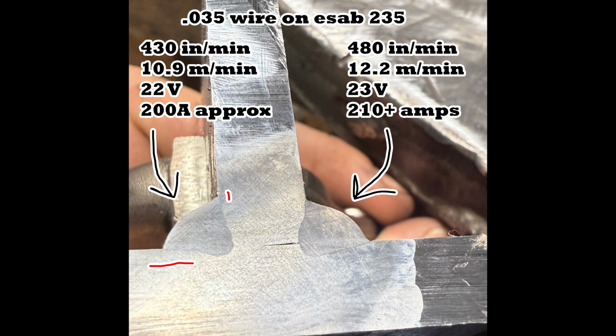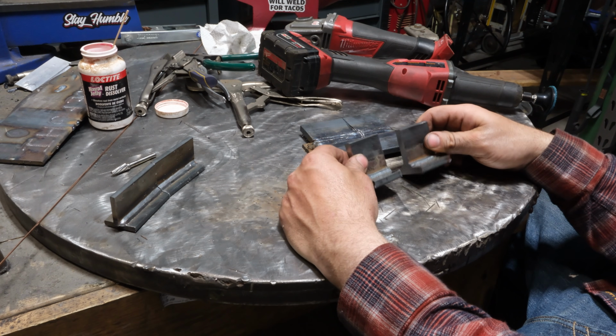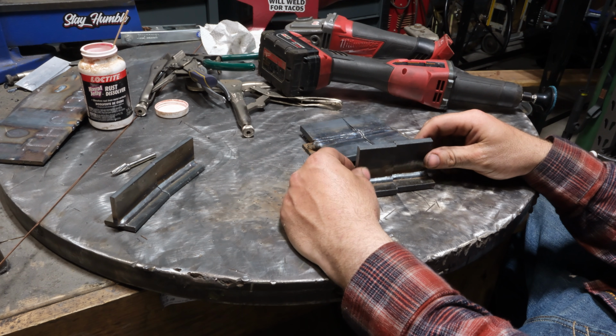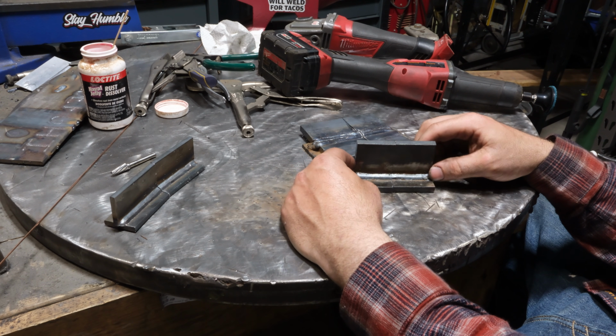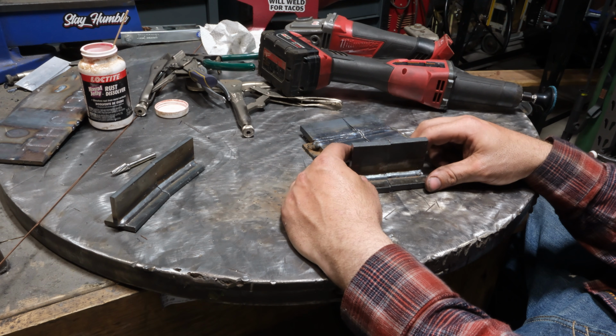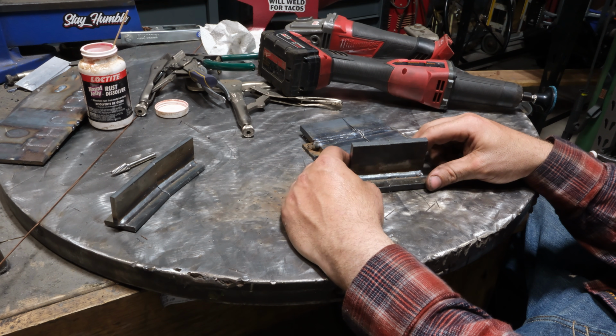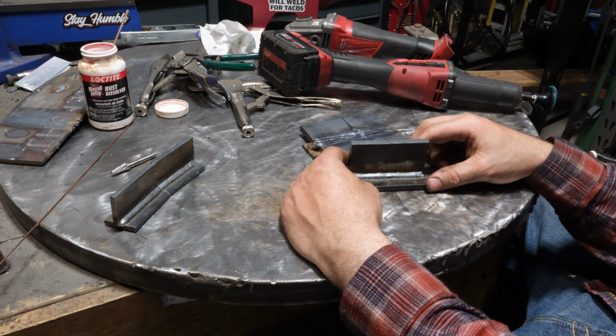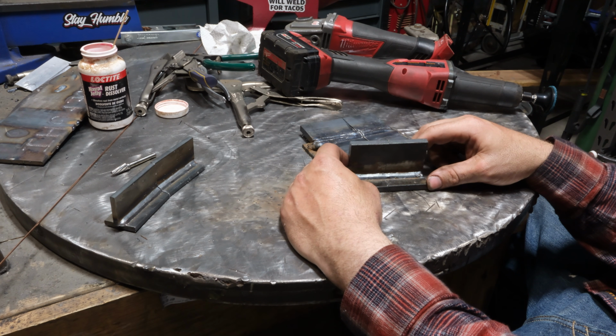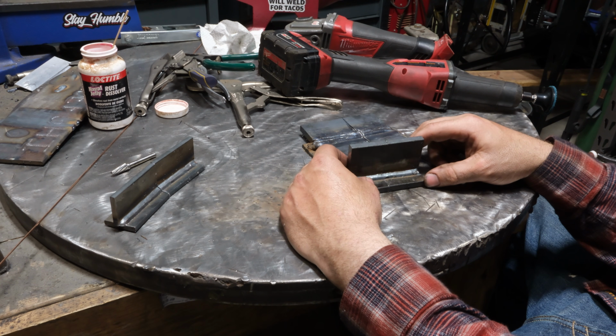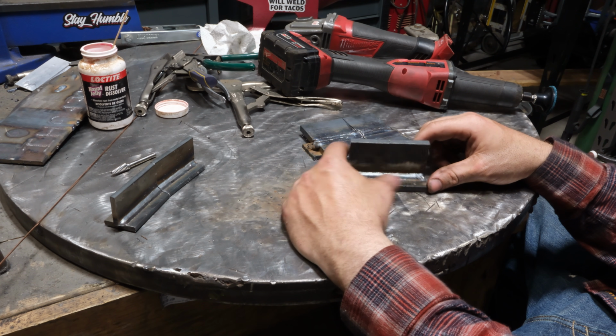And that's why it's predominantly not used for thicker steel. The results on a cut and etch on a test weld is one thing, but the reality of the real world is another. So the colder settings, aka the maxed out 200 amp MIG welder, are a little bit suspect. They're not bad. I mean, the penetration is decent, but I don't like seeing straight lines on a sidewall as much as I saw on that, and that's a little bit more suspect to me.